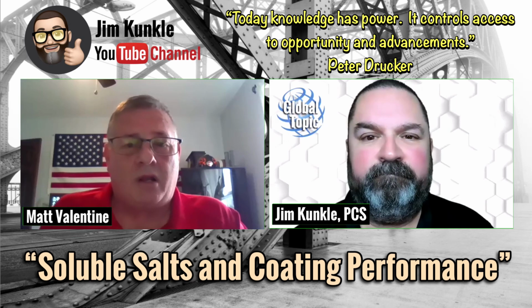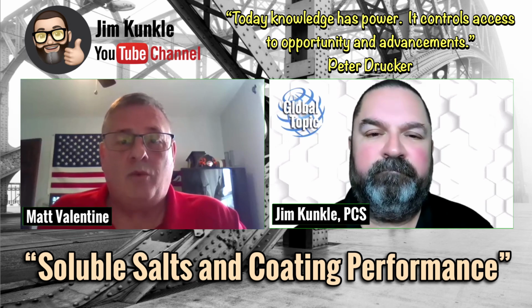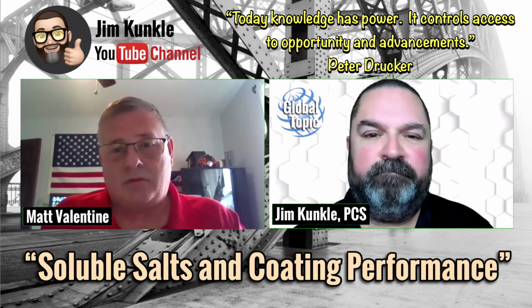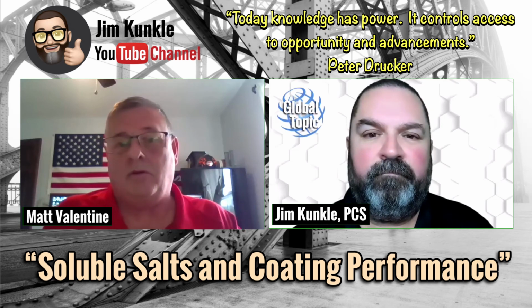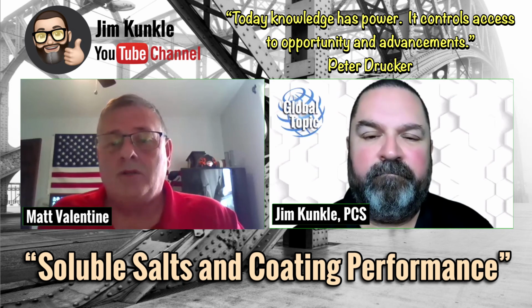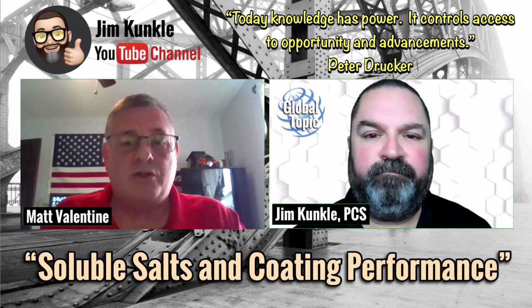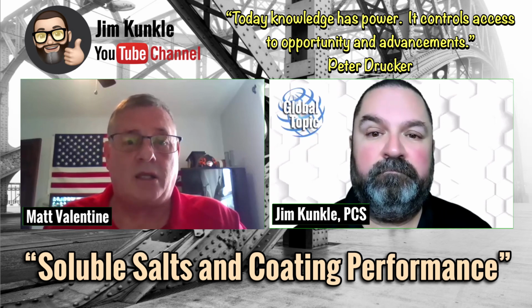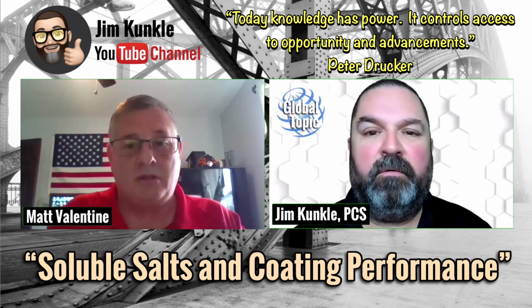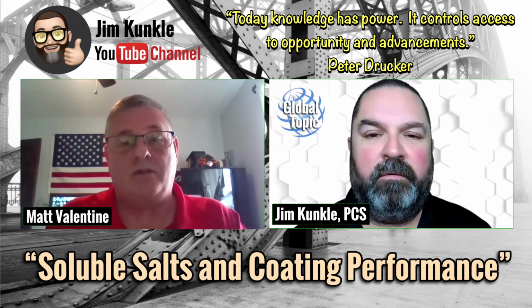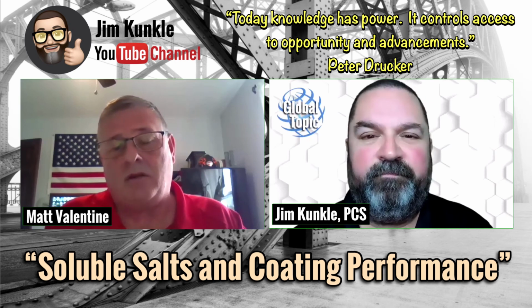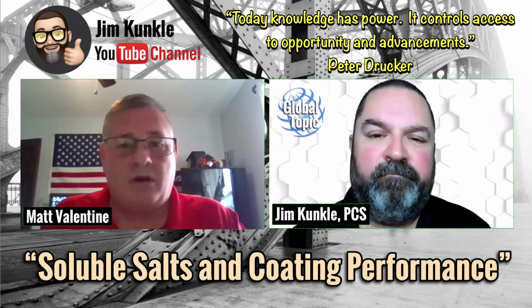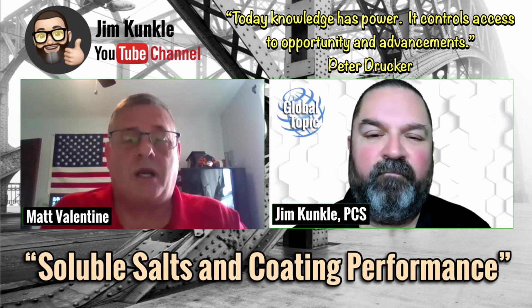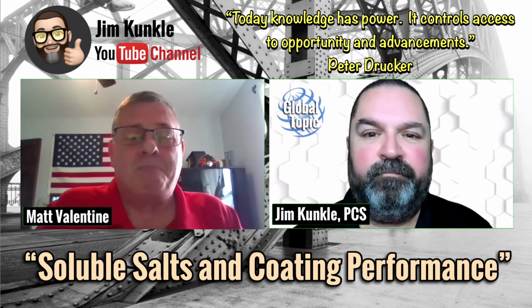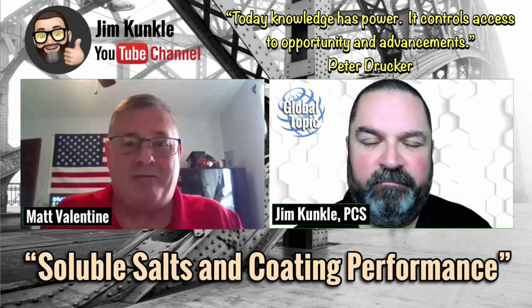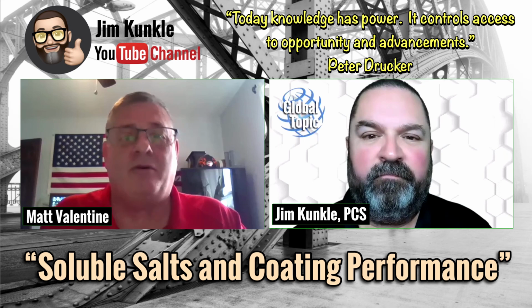So we developed a product called Hold Blast Vision. What that does is take off salts, but it doesn't take them down to non-detectable. It'll take them down to low levels. What that product will do for you is it actually has a visual inspection. You can take a black light and run it over the surface, and you can tell right away whether it still has residue on there or not. And the nice thing is, if you detect it, all you need to do is rinse it off again. We have on our website a video of that, and it shows real life at a salt plant in Cleveland, what it can do.